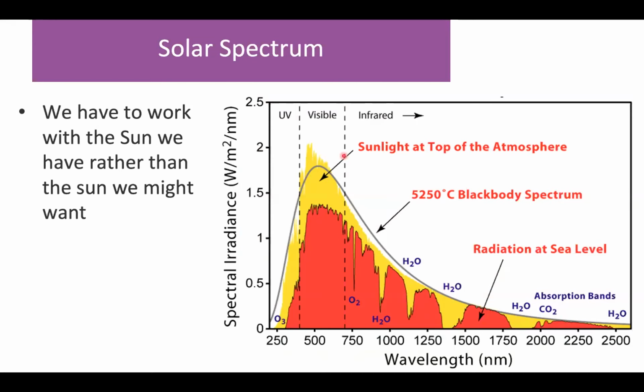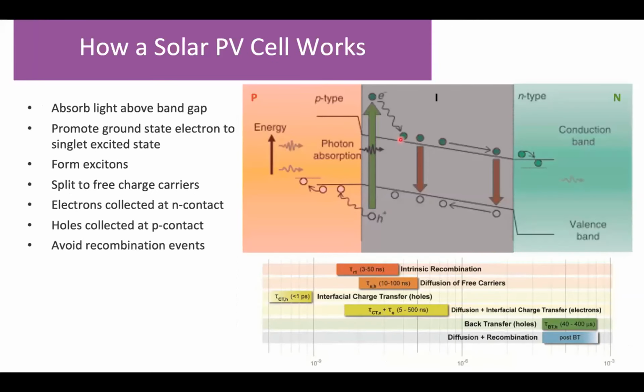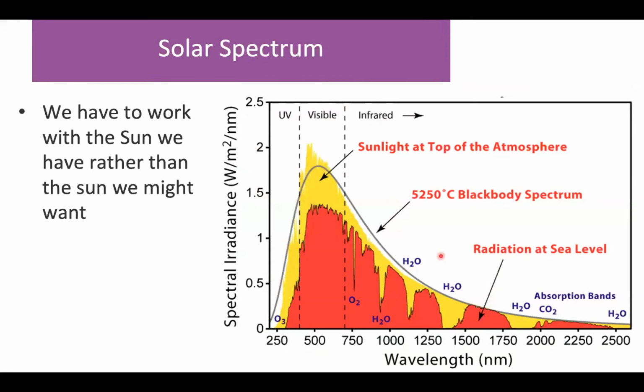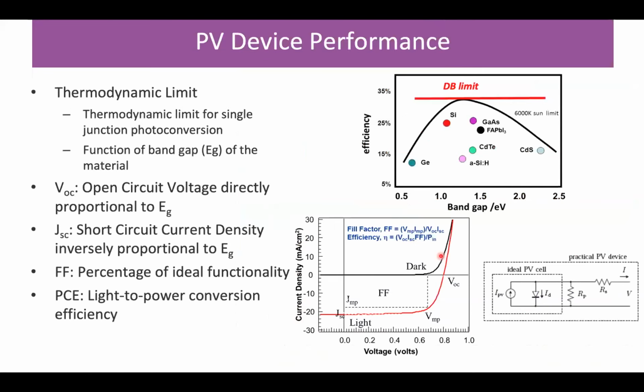So a lot of what we do in designing PV systems revolves around making the appropriate compromise between how wide or narrow we make this electronic gap, and then how well we do at these interfaces in ensuring that every carrier that's photogenerated is harvested. So in that sense, it's a fairly straightforward and simple activity. And if you look at the thermodynamic limits, or the detailed balance limit, this basically puts a cap on how efficiently you can extract this spectra depending upon what your electronic gap is and what the trade-off is.